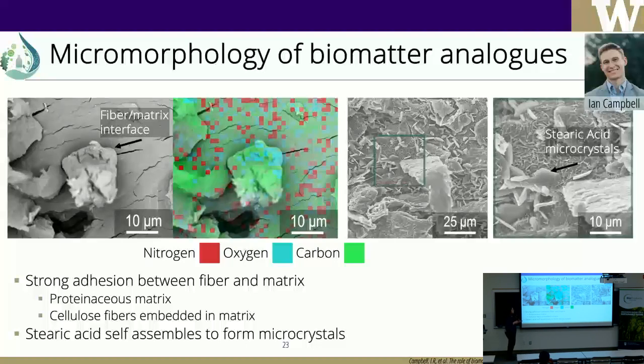Protein is going to be forming a matrix around cellulose. So if you go with EDX, you will see your nitrogen all around this bulk matrix. This is how we recognize that we have protein in a proteinaceous matrix. And then we will also see these characteristic microcrystals. These are going to be the self-assembled crystals from our fatty acid, stearic acid, which is what we would expect really, but they do migrate all the way up to the surface. Something that we haven't seen in real biomass, but we do see it in our simulation system.